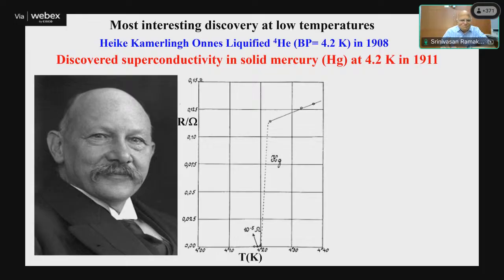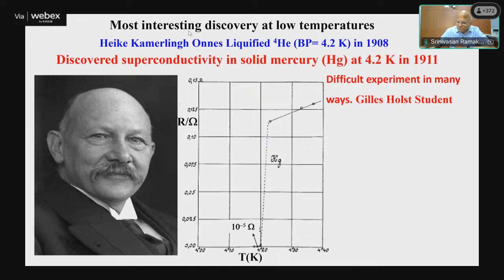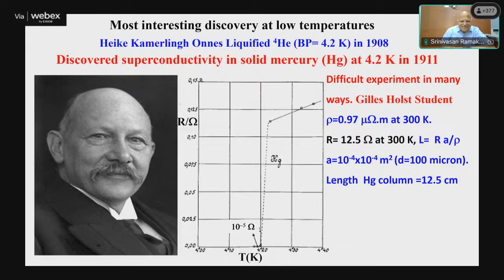But what many people don't tell you is how difficult this measurement was. We have to measure down to something like 10 microohms, and that is nearly 100 years ago. So it was a very difficult experiment in many ways. Gilles Holst was a student of Kamerlingh Onnes. Somehow he didn't feature in the Nobel Prize list. The difficulty is that mercury is only about 1 microohm meter at 300 K. As you cool this mercury, its resistance goes down by a factor of nearly 100 as you go towards 5 Kelvin or so. So we need to have sufficiently large resistance at room temperature.